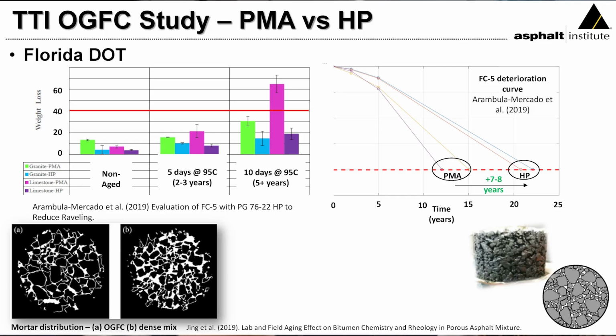So another study that was done, conducted by TTI, was around open graded friction course durability. And I know that's something that the state of South Carolina is very familiar with, that these particular mixes have a significant issue with durability. Now, Florida is actually one of the higher performing states for open graded friction course. I think they're getting about 12 years average lifespan. I know states that are not even getting 6 years. So they're actually doing pretty good, but even with 12 years, they're looking to get more. So they did this study.